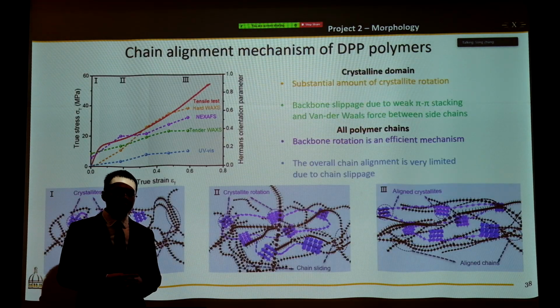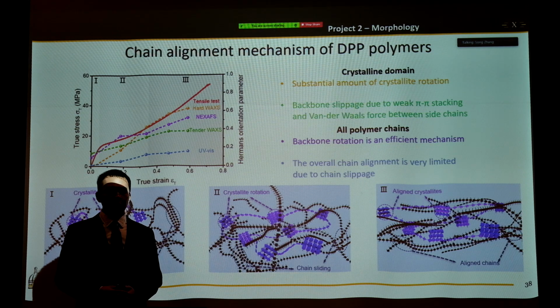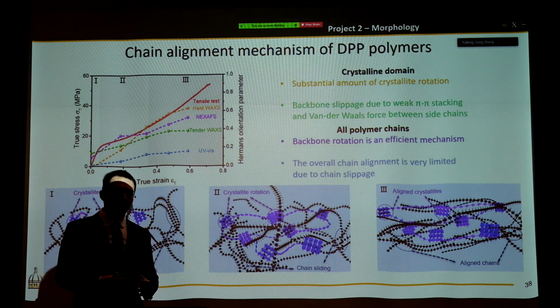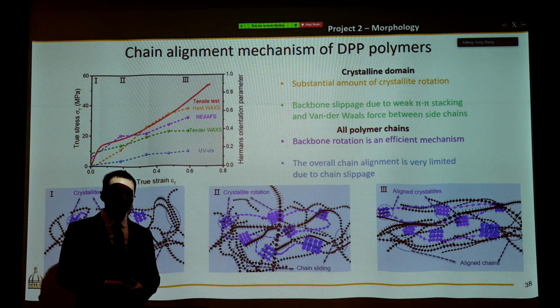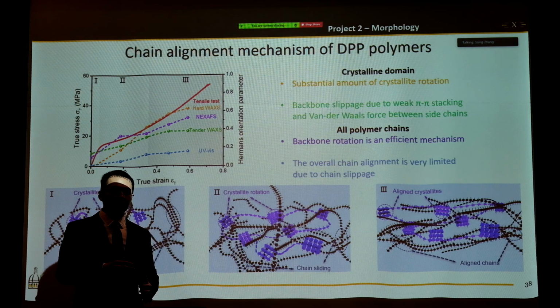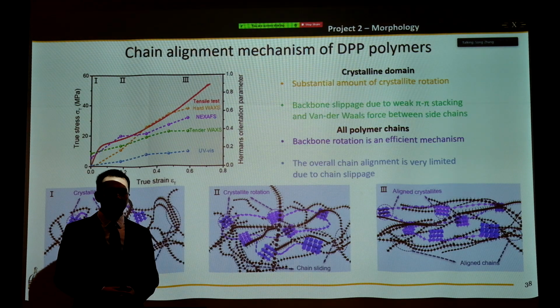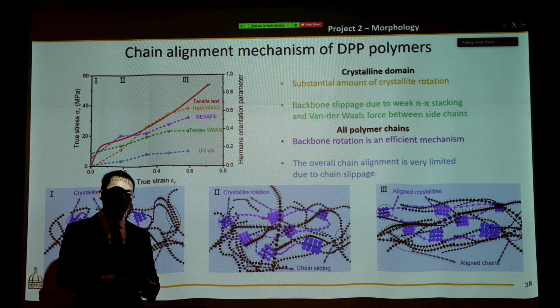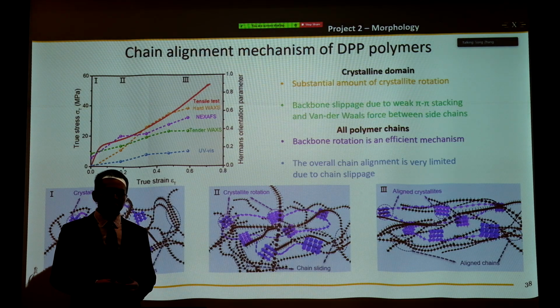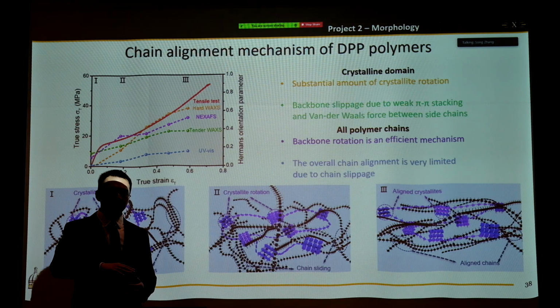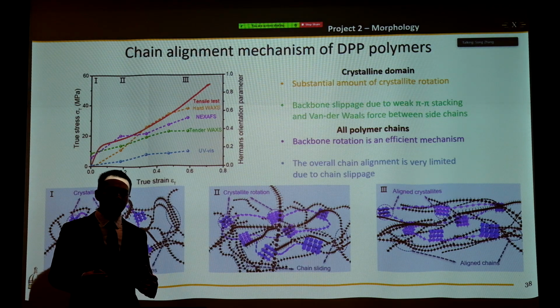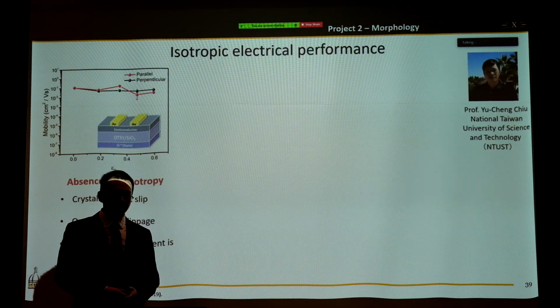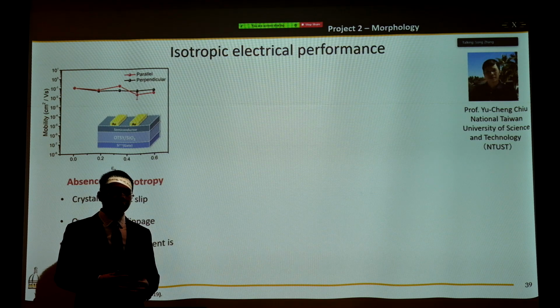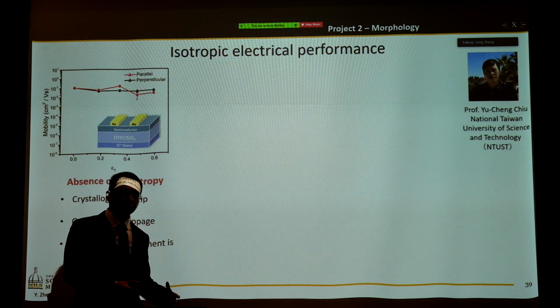Okay, now let me summarize the chain alignment mechanism for donor acceptor polymers. For different regions, they are very different from each other. From a crystalline domain, you can see the rotation behavior. You can see the backbone being extracted out of the crystallite. From all the polymer chains, you can see the backbone rotation, but the alignment of the average polymer chain is very limited.